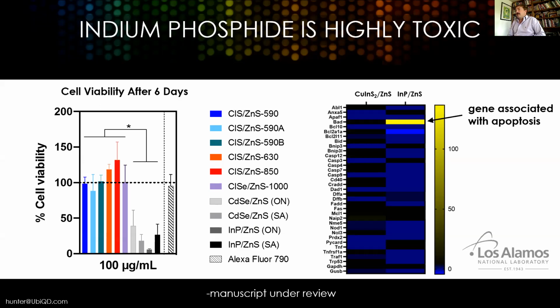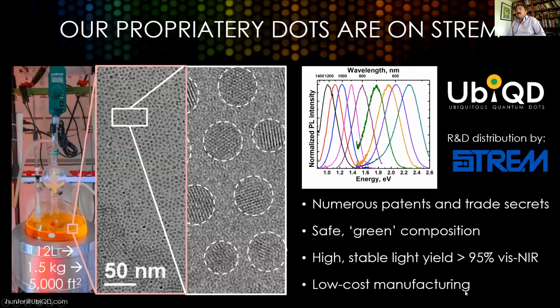So it really shouldn't be surprising given the fact that the phosphine precursors that are often used are also used in fumigation for pests, to remove pests. And it's well known that phosphides can form phosphine in the digestive system. So actually zinc phosphide is frequently used as rat poison. So I don't mean to throw indium phosphide too much under the bus, but just to make sure that we're getting our facts straight about the toxicity of this cadmium-free material, in some cases more toxic than the cadmium-containing materials.